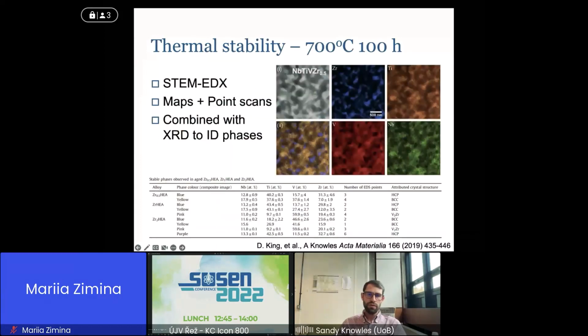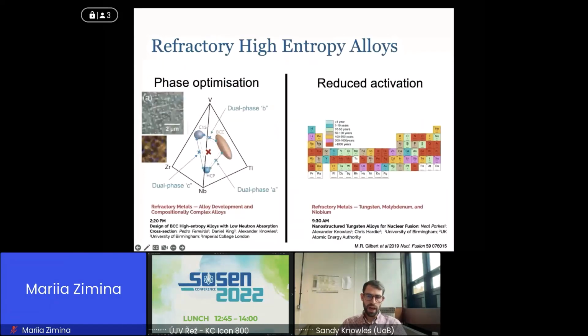In this case, the fact that we have multiple phases is maybe not a problem. We're also interested in high entropy alloys that have precipitates. In the same way we had nanostructured tungsten, why not have nanostructured high entropy alloys? So we could use these second phases for improvements in mechanical strength and high temperature strength, as well as for irradiation damage resistance.